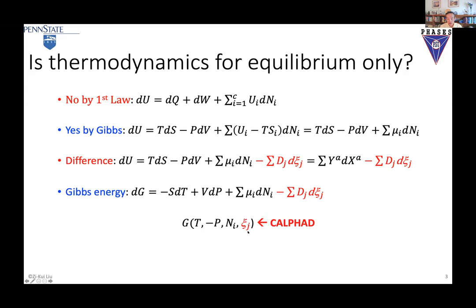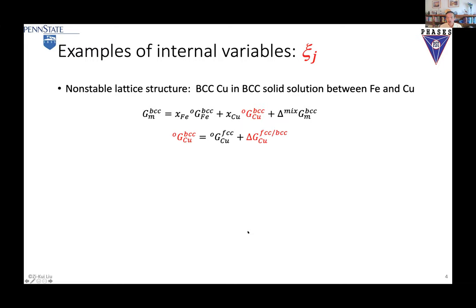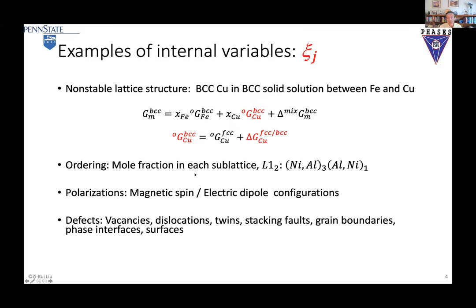CALPHAD is for both non-equilibrium and equilibrium systems, because it uses internal state variables. Key examples critical to CALPHAD modeling include lattice stability — for example, BCC copper, which forms in the BCC iron-copper solution, so we need the energy for BCC copper to model BCC solutions. That's lattice stability, defined by Larry Kaufman more than 50 years ago. In addition, we have sublattice compounds in the multi-sublattice model, with lattice stability in the end members. Then you have polarizations, defects — grain boundaries, vacancies, dislocations, twins — everything we deal with in materials science and engineering.